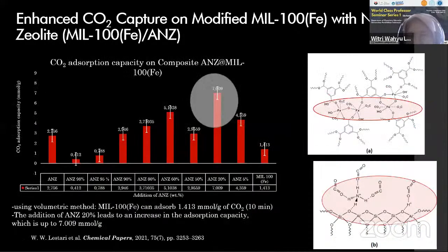And here, as you can see, the addition of natural zeolite, around 20%, in this MOF can give a significant enhancement for CO2 adsorption. Here we can see around 7 millimole per gram, which is quite high. Here is the active site for capturing the carbon dioxide.